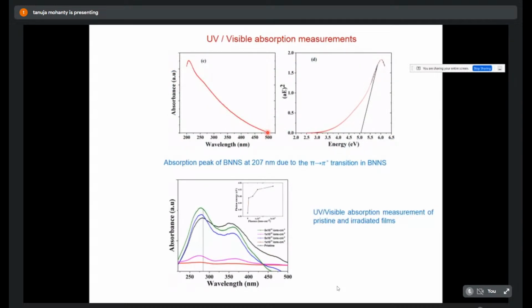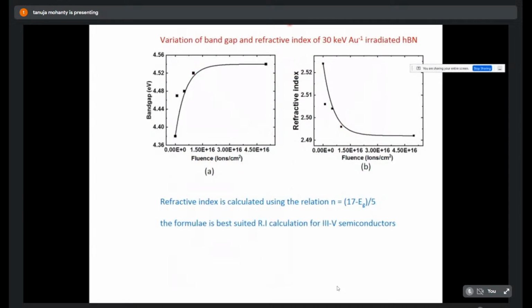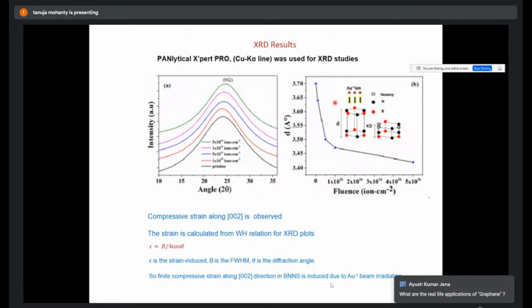And UV visible measurement also says how much the band gap is, whether it is changed, and what type of crystalline and irradiated films there are. The variation of band gap with refractive index we have also done with the Au-irradiated samples. The band gap and refractive index are inversely correlated, with n equal to 17 minus Eg by 5. That refractive index calculation can also be used for the III-V semiconductors, because the XRD is expected to change the 002 d value. So strain is calculated here using how much d is changing.